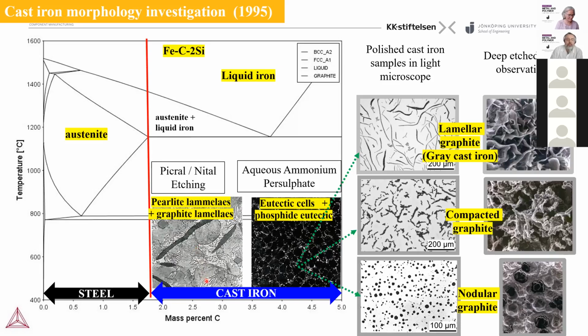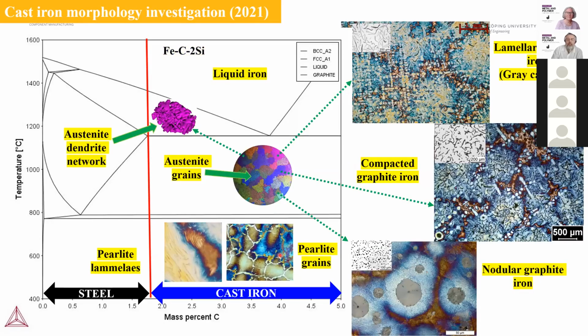In case you wanted to understand the graphite morphology and the eutectic cells, an aqueous ammonium persulfate solution was used for etching and promoting the phosphide eutectic, and that was the way to count the number of eutectic cells. So this was our knowledge about 20-25 years ago, and fortunately after 25 years we have a completely different understanding of the morphology of cast iron.